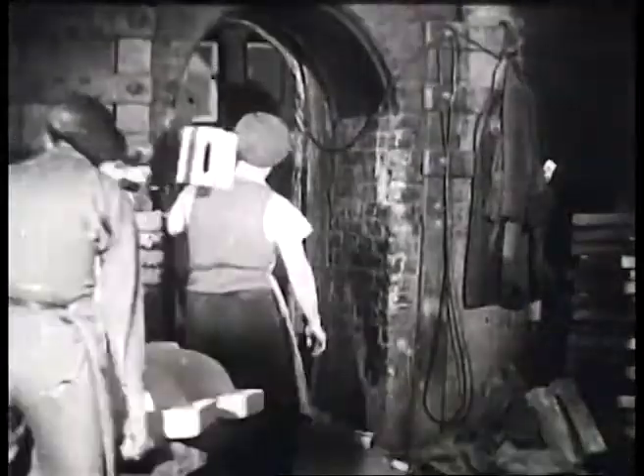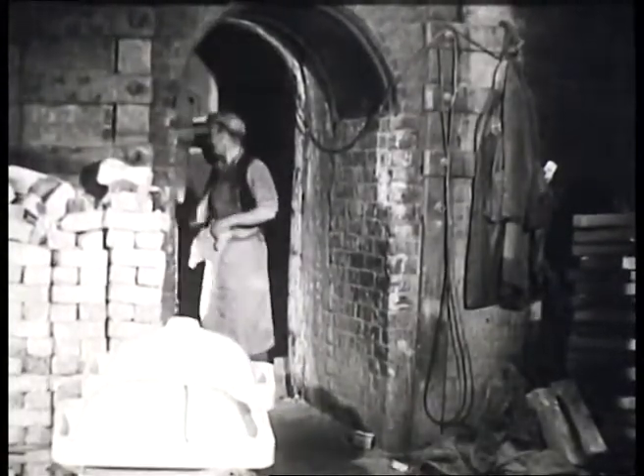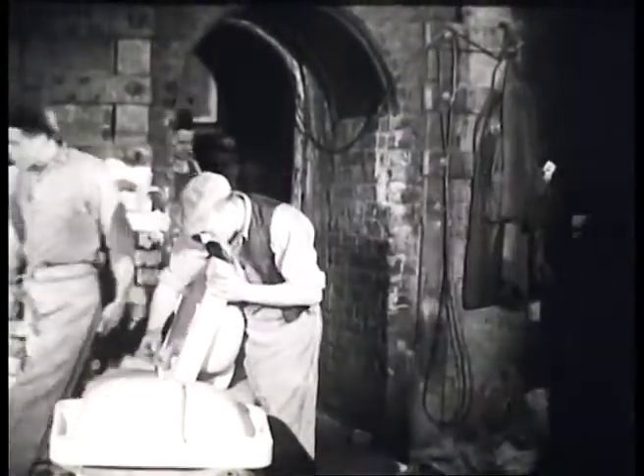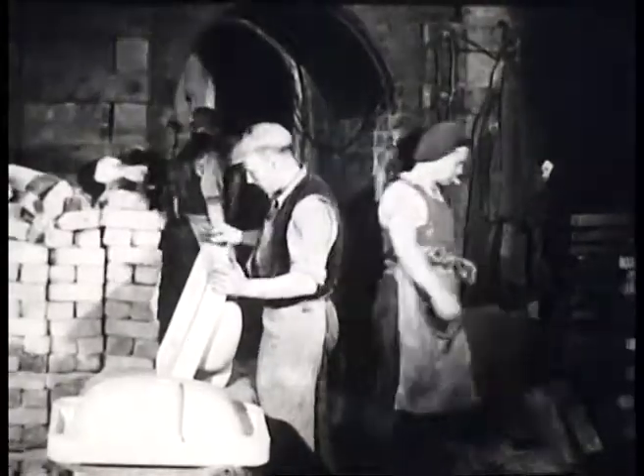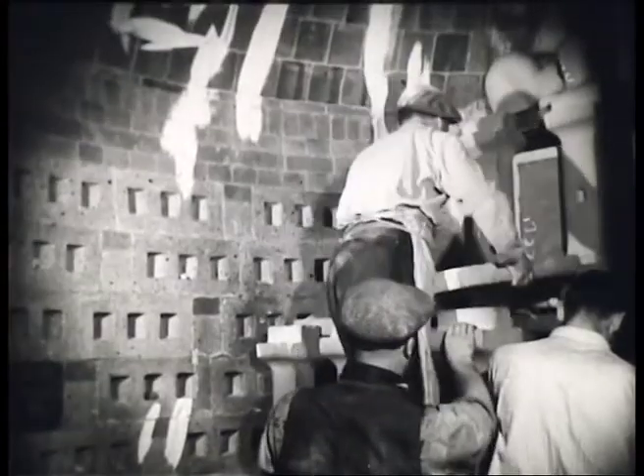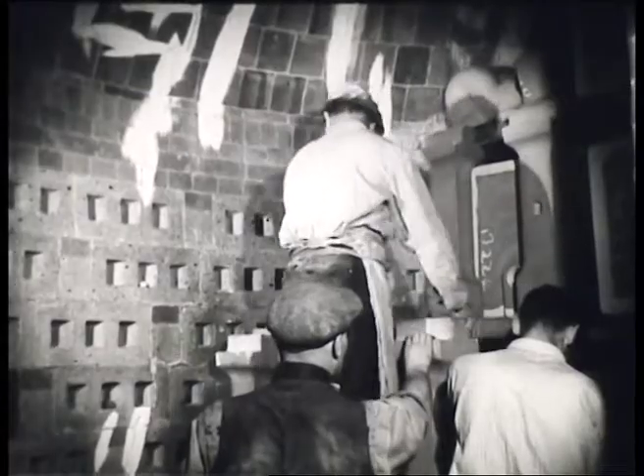There is much greater variety in the shapes and sizes of fire clay ware than exists in other sanitary pottery materials. This means that, generally speaking, it is easier to fire it in intermittent kilns. These allow more latitude in utilizing space than standard-sized trucks, which have to pass through a tunnel kiln of uniform cross-section. Setting ware in an intermittent kiln calls for great skill and ingenuity on the part of the kiln men, especially as the tiers rise nearer and nearer the crown of the kiln.